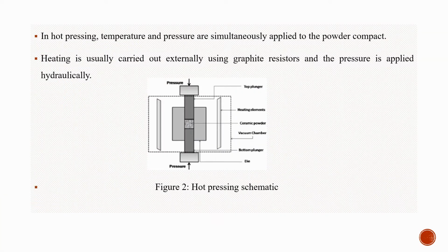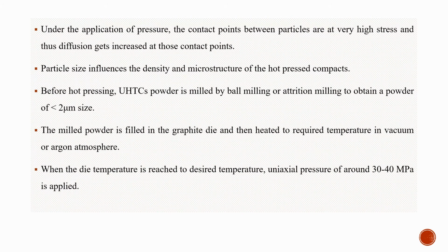In hot pressing, temperature and pressure are simultaneously applied to the powder compact. Heating is usually carried out externally using graphite resistors and the pressure is applied hydraulically. Figure 2 shows hot pressing schematic. Under the application of pressure, the contact points between particles are at very high stress and thus diffusion gets increased at those contact points. Particle size influences the density and microstructure of the hot-pressed compacts.